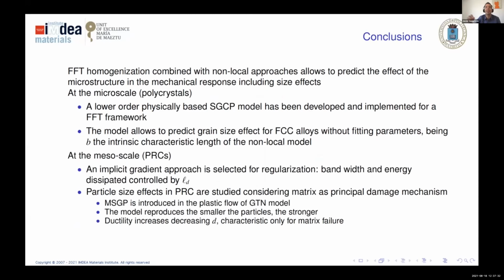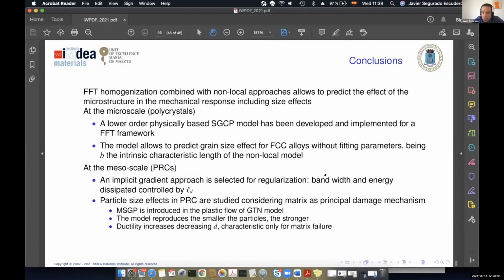And let's say that the main conclusion is that FFT homogenization is a very interesting tool to be combined with any type of non-local approaches through staggered models. I have not shown the techniques behind, but it's a good way to predict the effect of microstructure on the mechanical response, including size effects. And I'm just on time. Sorry for the delay, and that's all.